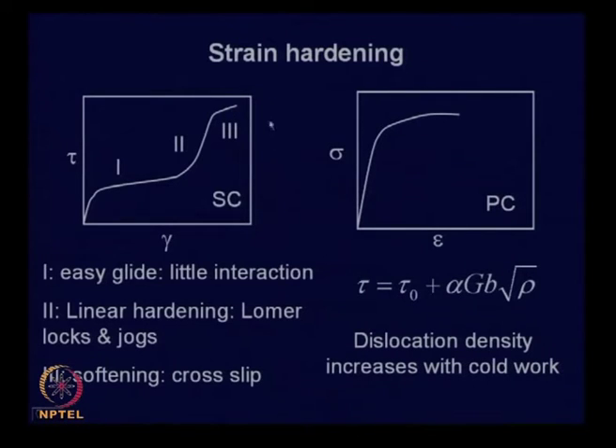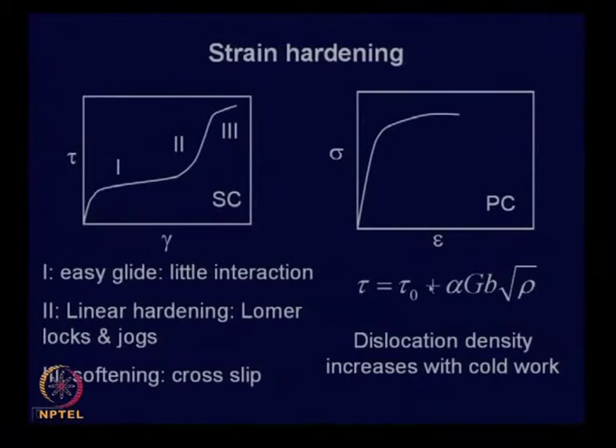So, this is the third stage, and in general this is the behavior in a single crystal, but in a polycrystal you have a large number of grains. So, you do not see these 3 distinct stages. What you see is a typical stress versus strain plot in case of a polycrystalline material, and here the total strength of the material will be determined by the dislocation density. Higher the dislocation density means you have more dislocations in the slip plane, and because of the dislocation interaction, it forms tangles of dislocations, and what is more important is if the dislocation density is increased, the distance between 2 dislocations also will decrease. The distance between dislocation nodes will decrease, and it is possible to show that the strengthening is proportional to square root of dislocation density.